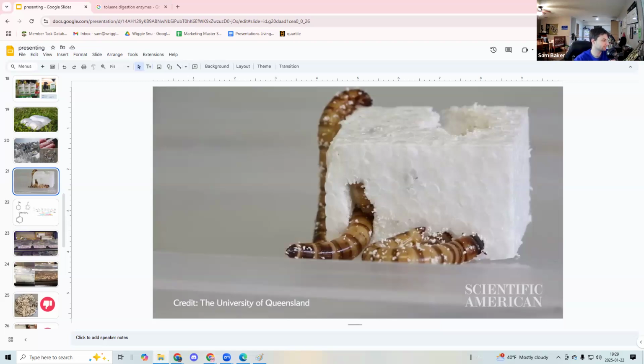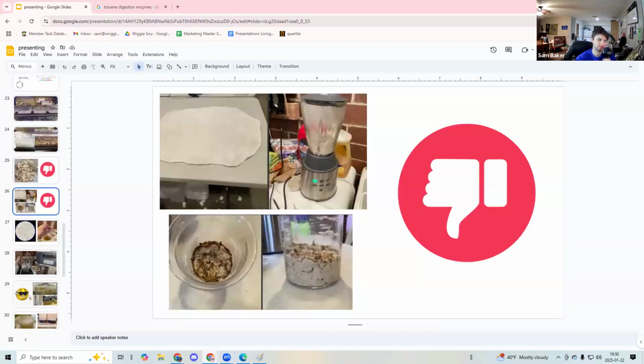Well, if we shrink the plastic down, we get it to a really small size. We find that, yes, you do get the worms eating more plastic per bite, but you also find that the worms are much more likely to choke and die on the material, because denser plastic means much harder to chew plastic, and the worms are still trying to chew it. And so, as a consequence, that doesn't really work either, which is really, really unfortunate.